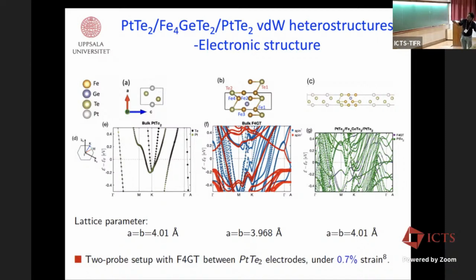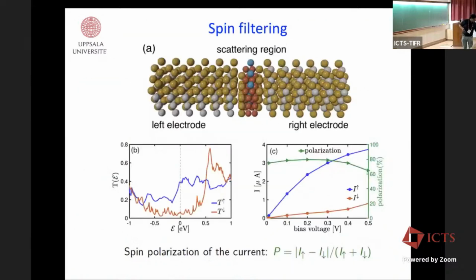You have the scattering part here, the magnetic system, and you have these platinum ditelluride leads. You can see a fancier picture here. So basically what is calculated is the spin polarized transmission. You see that at the Fermi level, at zero bias, the spin up has a very high value compared to the spin down. And that's why you can expect the spin polarization of the current can be quite high. It is not 100% for a monolayer, but if you use a bilayer, it is nearly 100%, 97% spin polarization that you see.